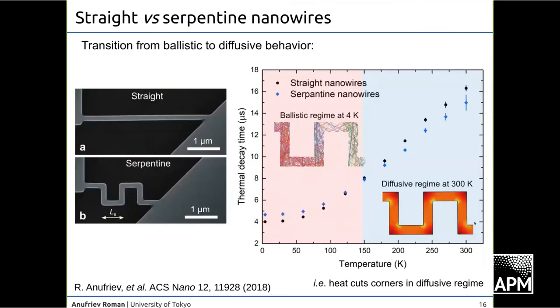Now let's plot this decay time on the y-axis and increase temperature. We can see a very interesting effect. At low temperature, as I mentioned, black is below the blue. Blue means serpentine and black means straight. So straight is faster than serpentine. It's semi-ballistic. As we increase temperature, the difference between them almost disappears at 150K. But then what happens is even more interesting. They cross. And now at room temperature, the serpentine one is faster than the straight. This is called the corner cutting effect in the diffusive regime.